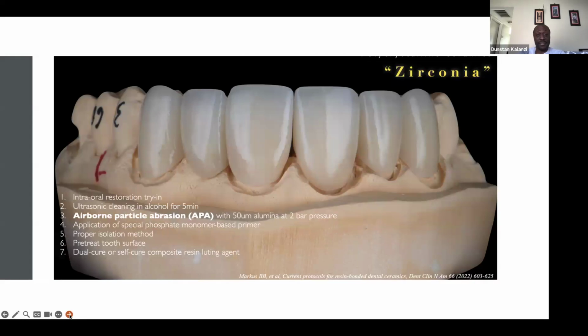For zirconia, it's different. Zirconia, as we said, you need to sandblast. It's not bondable, it's not etchable. You have to sandblast the preparation surface. So you can have a small machine, a sandblaster, basically a gun that can treat the surface. And then you can apply a little bit of bond, and then you cement the restoration.